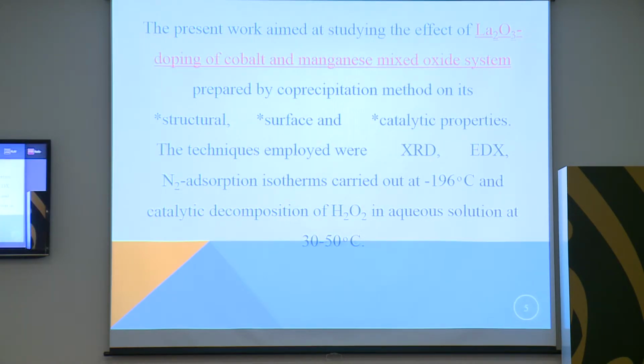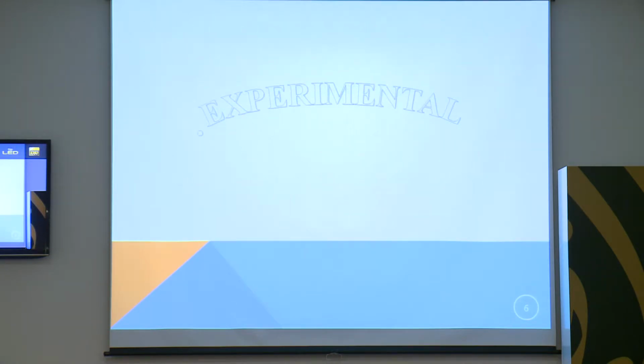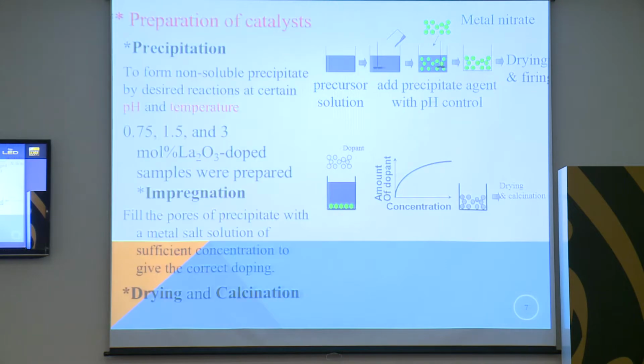The techniques employed were XRD, EDX, nitrogen adsorption-desorption, and surface area measurements carried out at -196 degrees. The catalytic decomposition of hydrogen peroxide in aqueous solution was studied at 30 to 50 degrees. The experimental part to prepare our solid catalyst goes through 3 steps. The first one, by co-precipitation method, we prepare the cobalt manganese mixed oxides from a precursor solution of metal nitrates by using sodium hydroxide as a precipitating agent at pH equals 8 and temperature at 70 degrees.